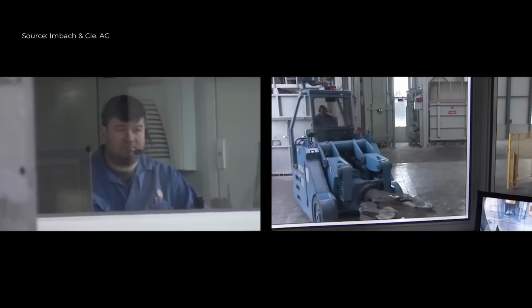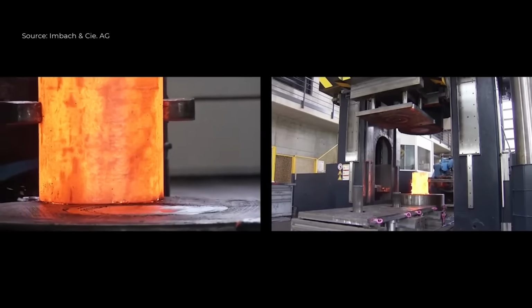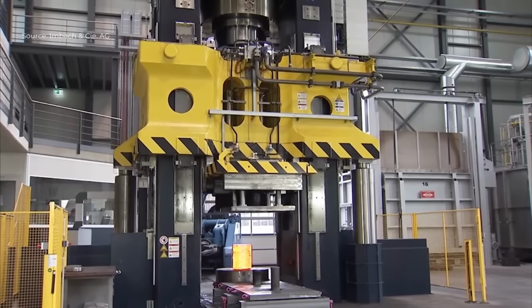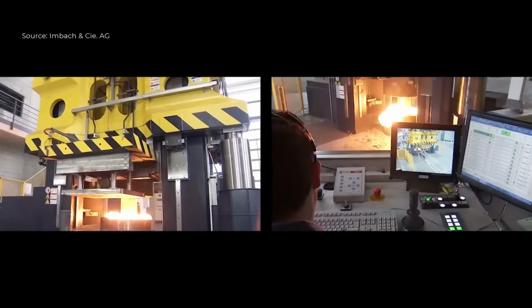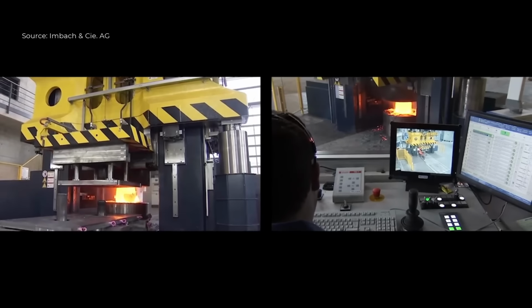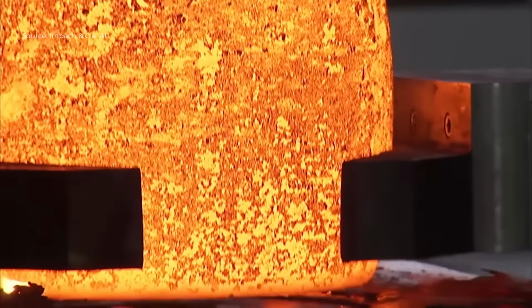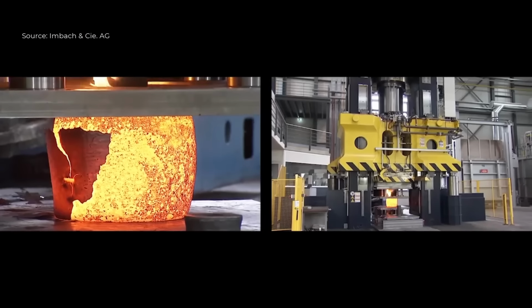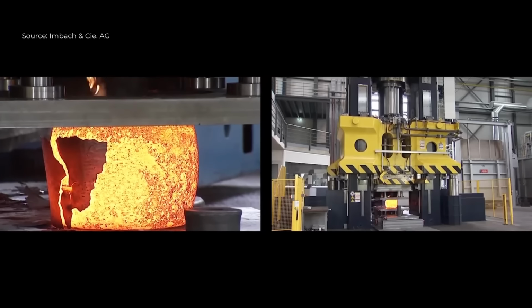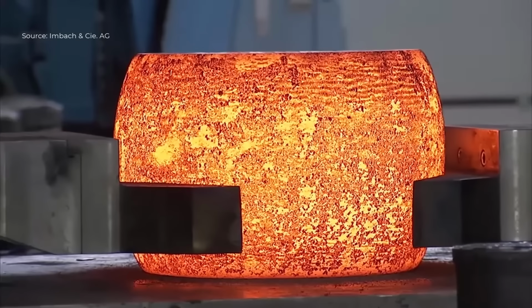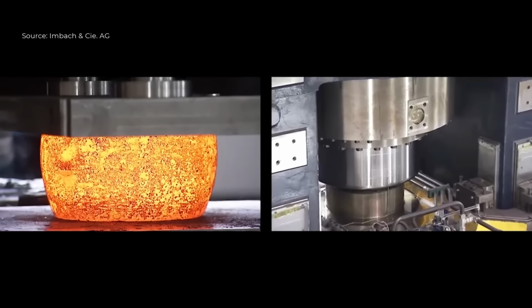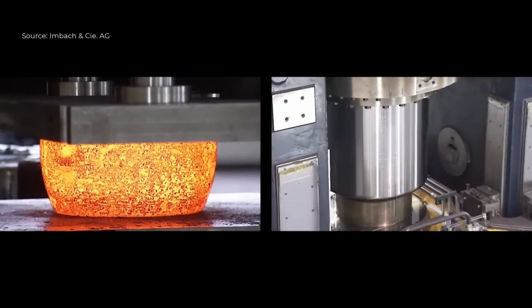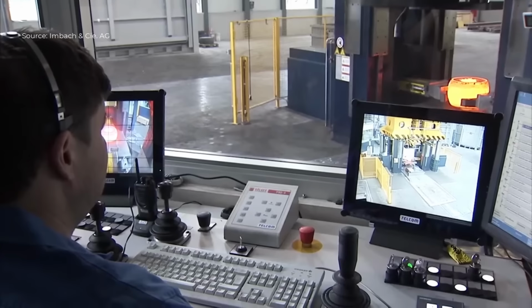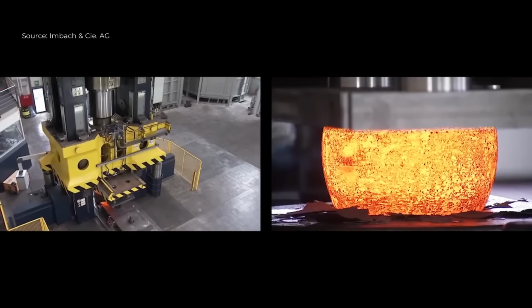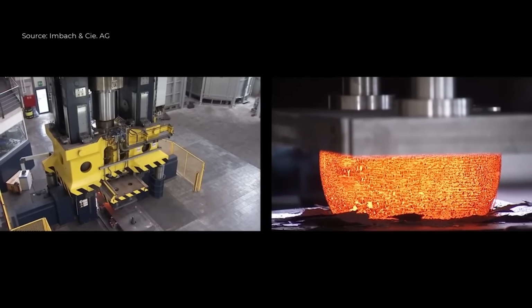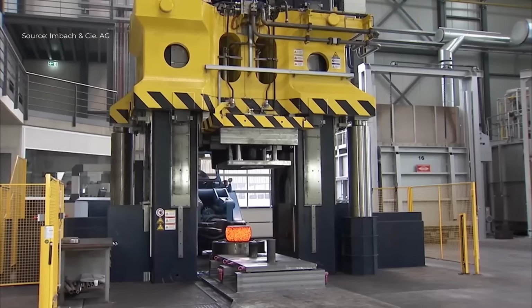The core of Imbach's production lies in hot deformation, where metals are heated to high temperatures to increase ductility and then shaped under massive pressure. In the open die forging process, the material is placed between flat or contoured dies and hammered or pressed until the desired geometry is achieved. This method is ideal for producing high-strength components in small batches, from 2 kilograms up to 4,000 kilograms, with a fiber orientation aligned to stress directions, providing superior mechanical properties. A programmable 3,000-ton press ensures high efficiency and reproducibility during this stage.